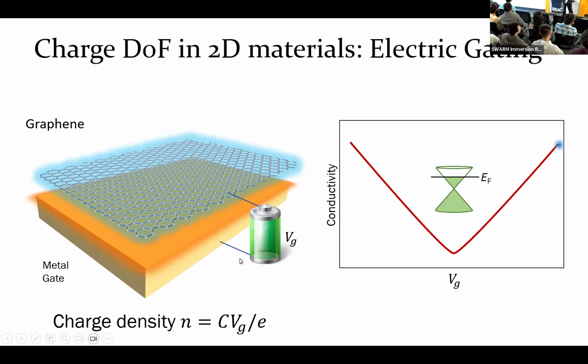And if you change graphene to a different 2D material, like MoS2, then you can get a real MOSFET with a large on-off ratio, and so on and so forth. But all of these rely on basically the fact that in 2D materials, the charge density can be tuned very easily just by putting a nearby gate, and you don't need to dope it. You don't need to do chemical doping. These are all electrostatic gating.